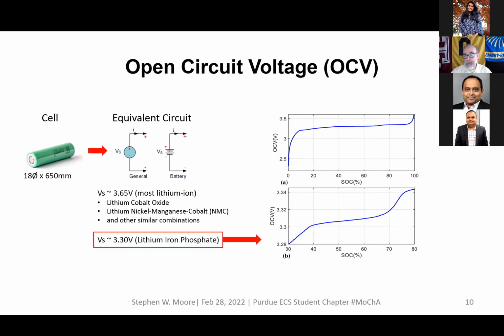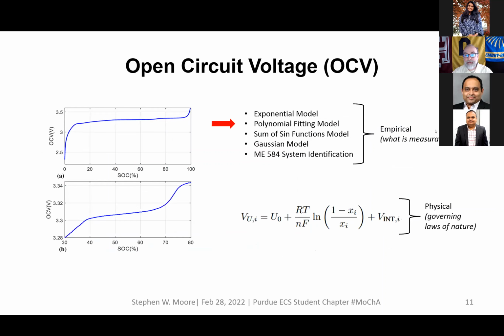But if you zoom into that flat curve, you'll see that in the lower image where it's zoomed in, the voltage goes up to about 3.3, then it goes up, and then there's another inflection point at 3.32, then it goes up again, and then there's another inflection point at 3.34. This is all happening in the millivolt space, but it still makes the voltage rather difficult to follow.